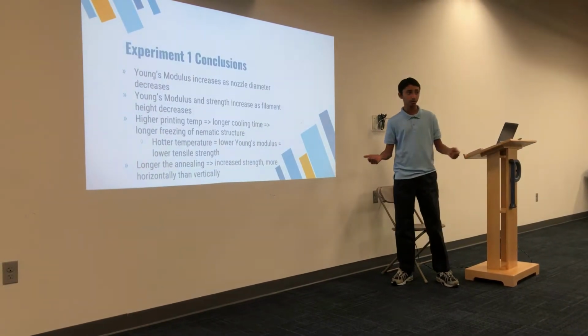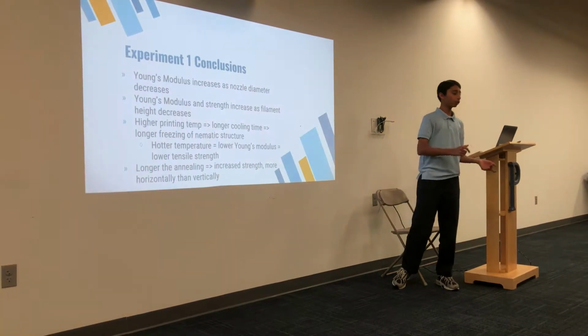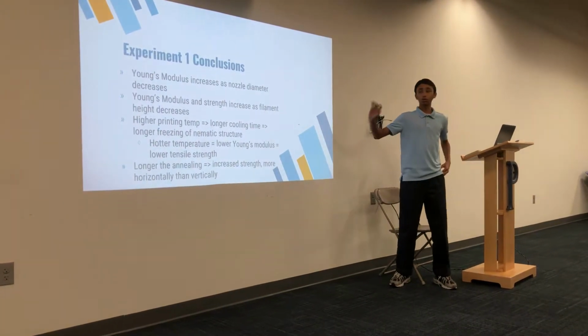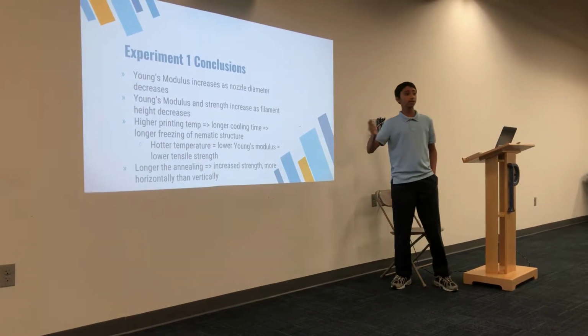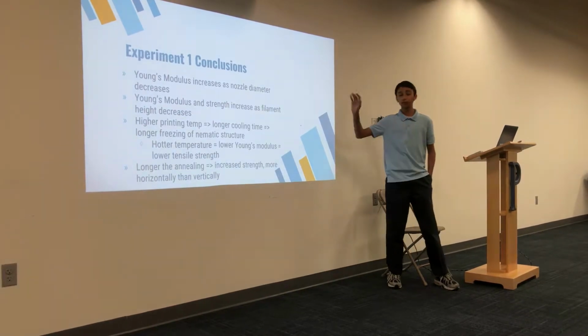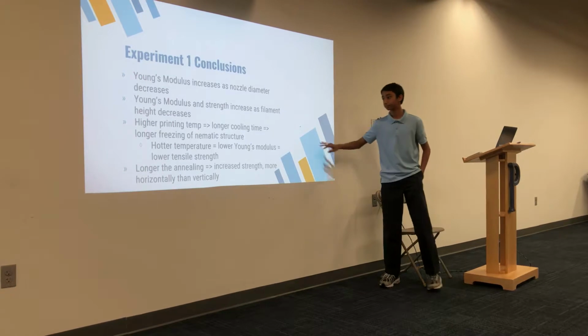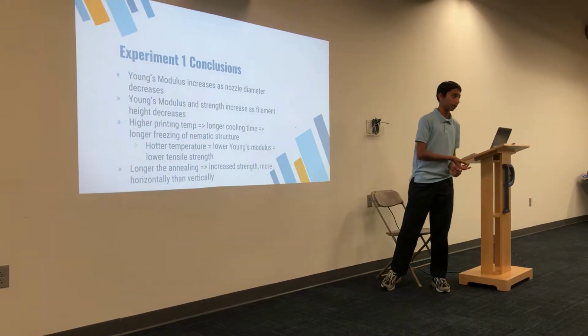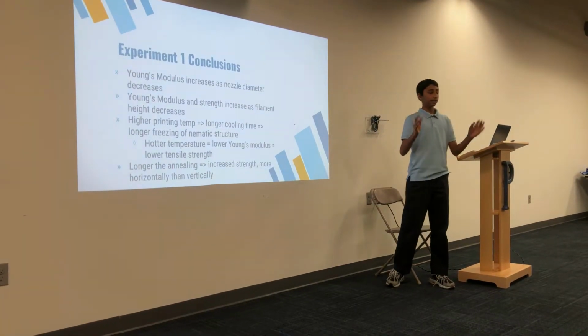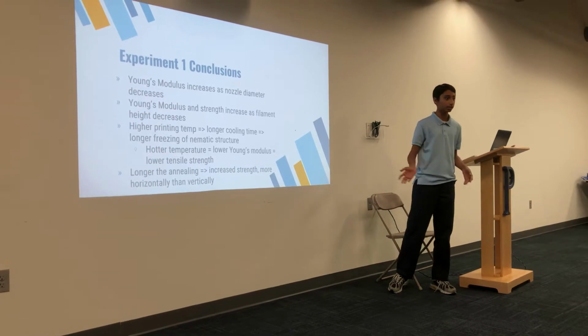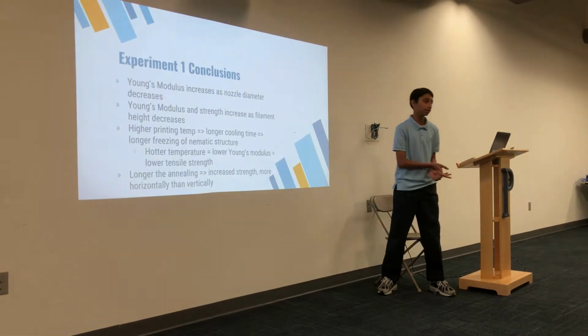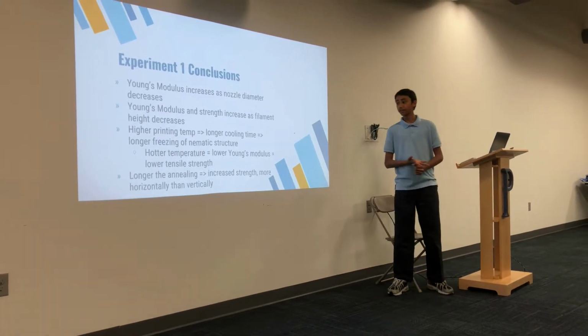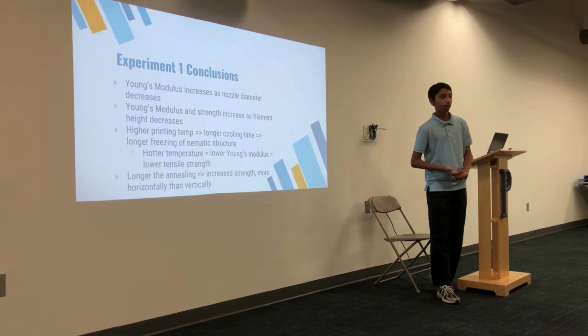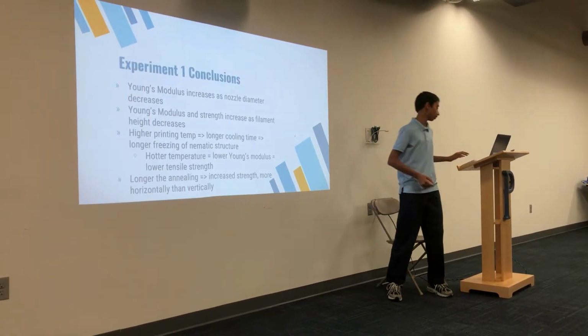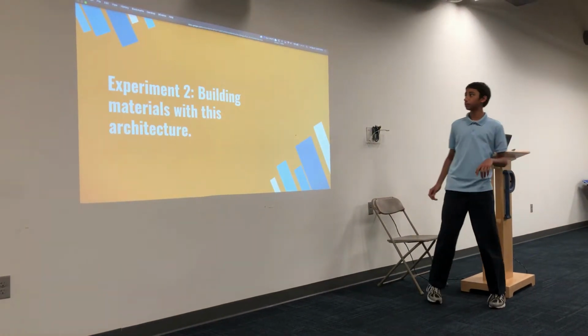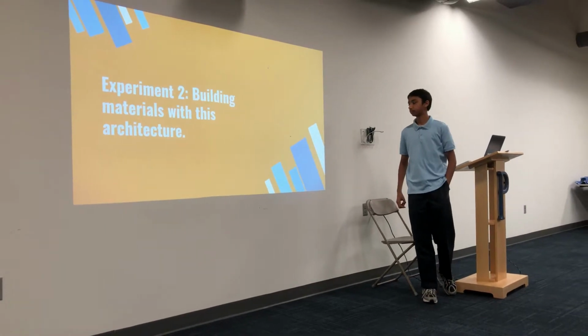We talked about the freezing of the nematic structure: when those molecules come out of the extruder and they cool down, they kind of get frozen into those orientations. So when you heat up the filament more and more, and it takes longer and longer to cool, it's going to take a longer amount of time for those molecules to freeze into their nematic domain. And this is going to lead to a lower Young's modulus, right? Because now there's an increased likelihood that each of these individual molecules is off in different directions because they've had time to settle down, and that in turn is going to lead to less strength of the material. And then finally, the longer the annealing, the greater the strength of the material, especially horizontally rather than vertically.